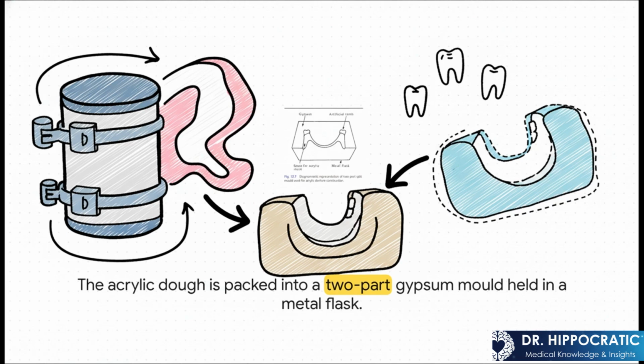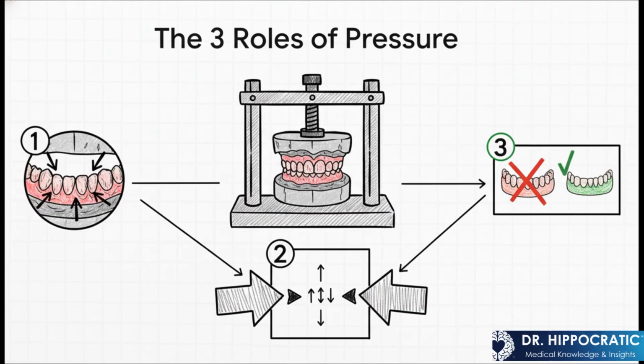This whole thing is then held in a heavy metal flask, which has to be strong enough to handle the incredible pressures we're about to apply. That empty space you see, that is the exact negative shape of the final denture. The key thing to remember here is that applying all that pressure with a bench press does 3 absolutely vital things. First, it forces that dough into every single tiny crevice of the mold, which gives us a perfect fit. Second, it helps compensate for that 5 to 6% shrinkage we've been talking about. And third, it makes sure the final denture isn't too thick, which would cause a problem we call a raised bite.